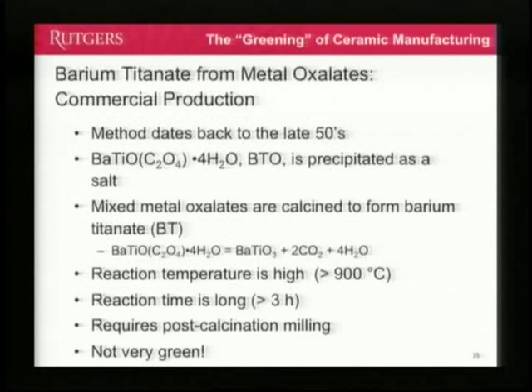Here's some neat work that Vahid Adakan did for his PhD, where we looked at this whole process of making barium titanate, BaTiO3, from this barium titanyl oxalate. So an oxalate is actually two CO2 molecules joined at the hip, so to speak. And these metal oxalates are calcined. So for every mole of barium titanate, you get two moles of CO2.